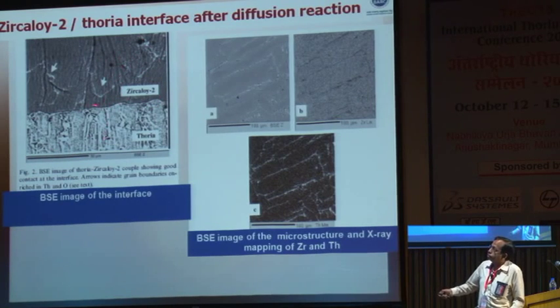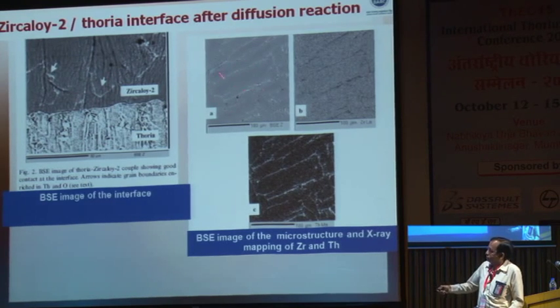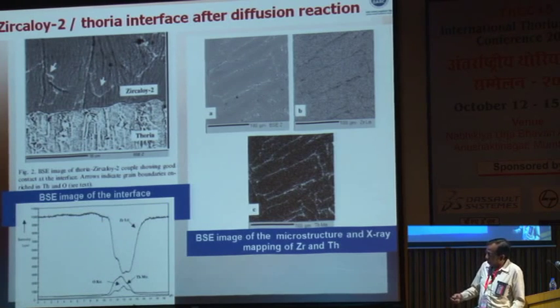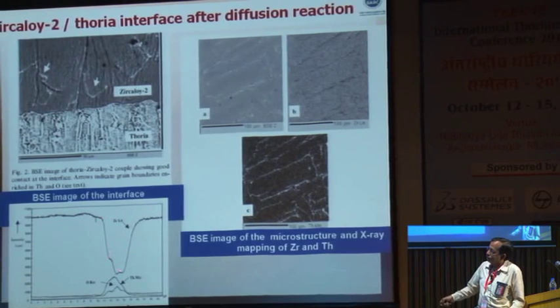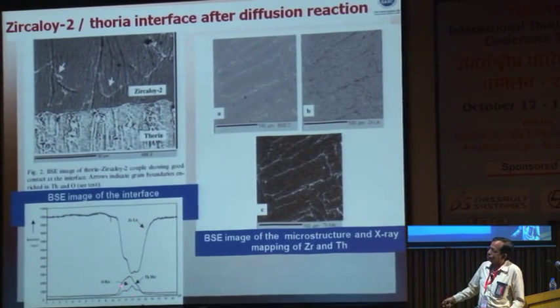So this is the zircaloy side, and this is the thoria side, and we could see that when the temperatures were raised in vacuum, thoria has diffused to the zircaloy grain boundaries. Thorium has diffused, and the thorium and oxygen contents could be seen in this viewgraph here. You can see that at the grain boundary, the amount of zirconium dips, and the amount of oxygen and that of thorium increases. So this is one aspect which is of concern, because one may think of putting a sleeve to prevent the diffusion of thorium into the clad, which is not desirable.